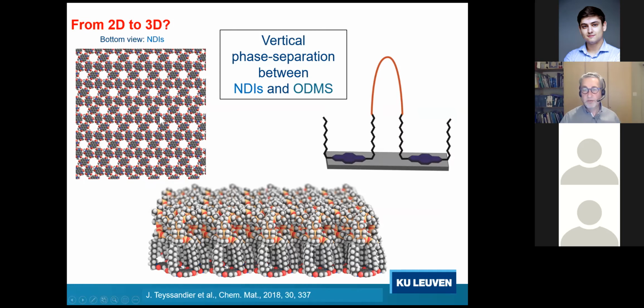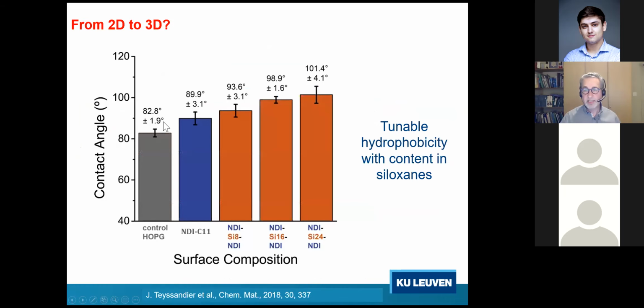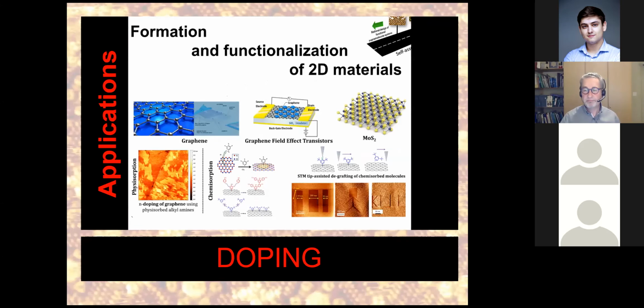Of course, these molecules differ in the length of the dimethyl siloxane groups. And indeed, if we then look with contact angle measurements, we also observe this, that the molecules with the longest dimethyl siloxane groups show the highest contact angle. So this is the first type of, you could say, application.